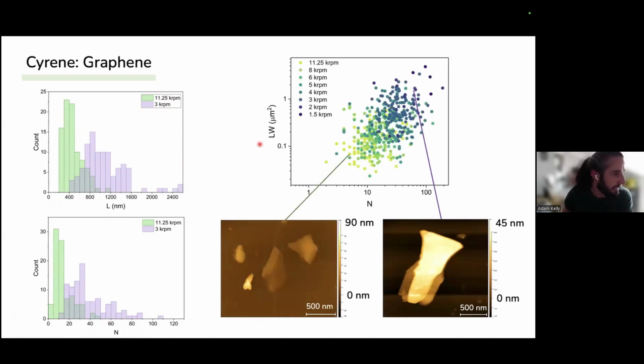So by plotting the nanosheet length and width, which is a proxy for the area of the basal plane, against the nanosheet thickness, or sorry, layer number, for all of these centrifugation speeds, we get a cloud that looks like this. So all the high speed, thin, and small nanosheets are down here, and all the thick stuff is up here. So these are representative AFM images, but we see even up here at the top right, where the nanosheets are quite large and quite thick, you still get nice, clean basal planes in there. So you are producing nanosheets, they're just extremely large and chunky.